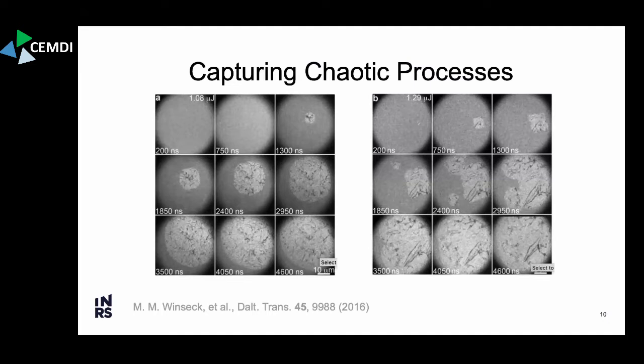What I'm showing here is actually the crystallization of a germanium alloy, germanium antimony tellurium, a GST, a phase change alloy. Anyways, it's a germanium alloy, and you're seeing it go from an amorphous into the crystalline phase based on laser radiation. This material is actually in DVDs and CD-ROMs, and this is how you write bits onto them. The 0 would be the amorphous region, and then you shine a laser on it and get it to transform into a crystalline region. Those two have different reflectivities, so you're able to write a 1 and a 0 based on the reflectivity.